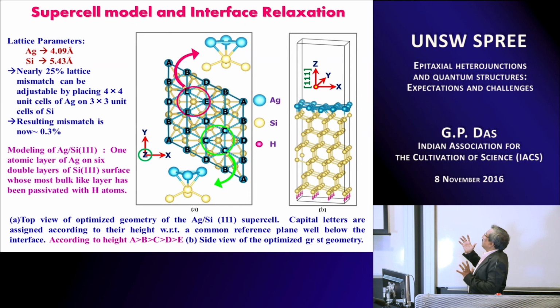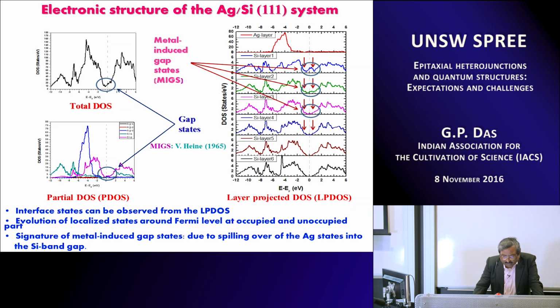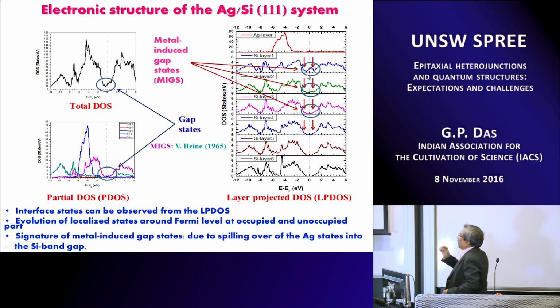We have done a full-fledged DFT calculation on this kind of interface, and you can see an interesting manifestation of metal induced gap states. Whatever I am showing here are the layer projected density of states. The one which is here is at the interface. So this is the silicon at the interface, and as you go away, this is the silicon which is farthest from the interface. You can easily see that the one which is farthest from the interface has the traditional 3-humped structure of silicon with a gap. However, when you come closer and closer to the interface, you can see that there are localized surface states or interface states which are developed, and it is those interface states which are responsible for the pinning mechanism.